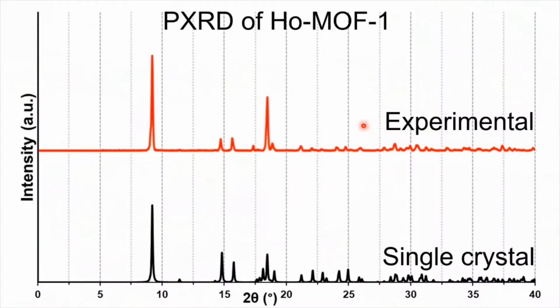And this is what I was talking about. I'm not going to show all the characterization for all of them, just for this one, so you understand what I was talking about. So once we get the single crystal, we can predict what the powder X-ray diffraction pattern will look like, and then you compare it, and you know if you're actually synthesizing the structure that you want. You have to look at these peaks, see if they match, and then you know you are producing your expected structure.